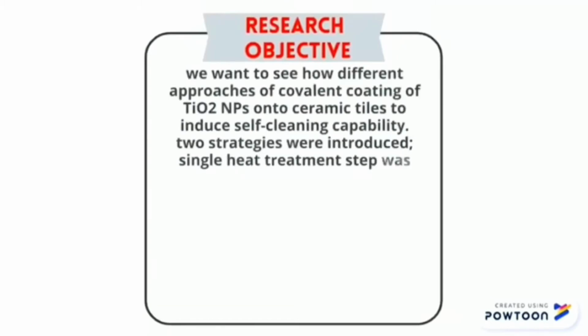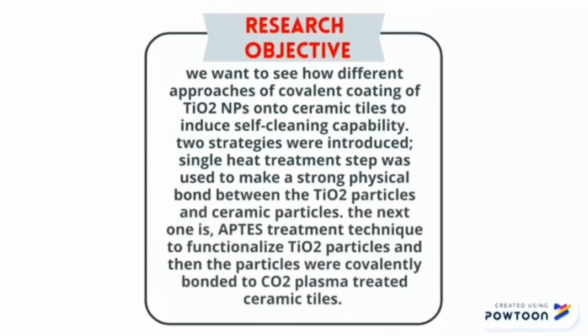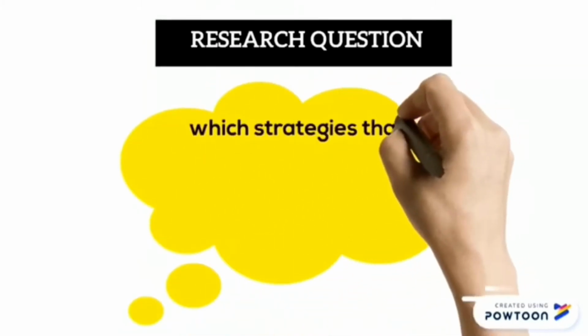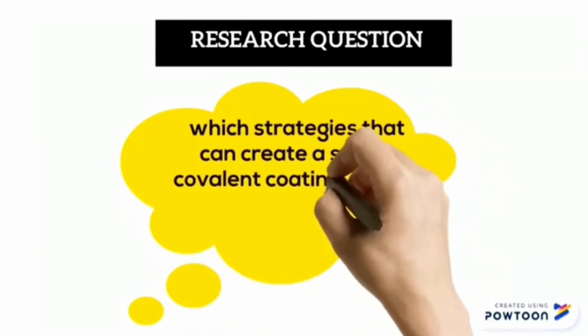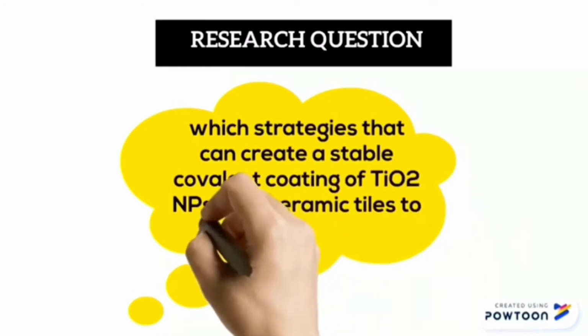We want to see how different approaches of covalent coating of titanium dioxide nanoparticles onto ceramic tiles induce self-cleaning capability. Basically, there were two strategies introduced. The first one is a single heat treatment step, used to make a strong physical bond between the titanium dioxide particles and the ceramic. The next one is we use the APTES treatment technique to functionalize titanium dioxide particles, and then the particles were covalently bonded to carbon dioxide plasma treated ceramic tile. So the question is, which strategy can create a stable covalent coating of titanium dioxide nanoparticles onto ceramic tiles to induce self-cleaning?